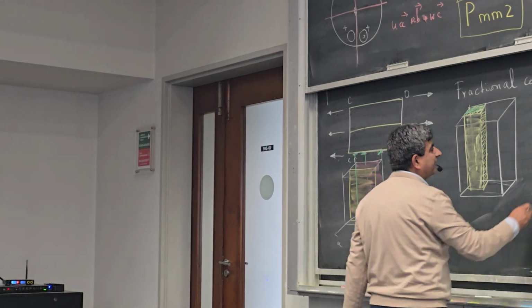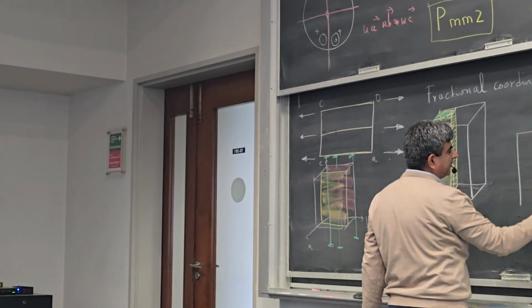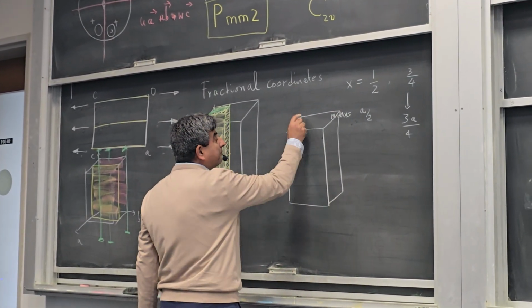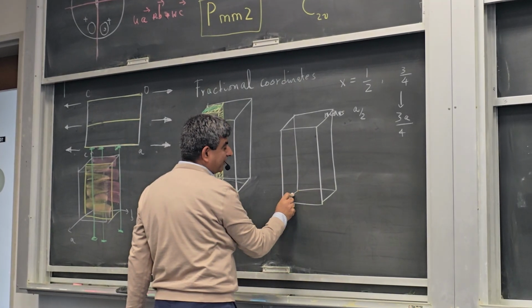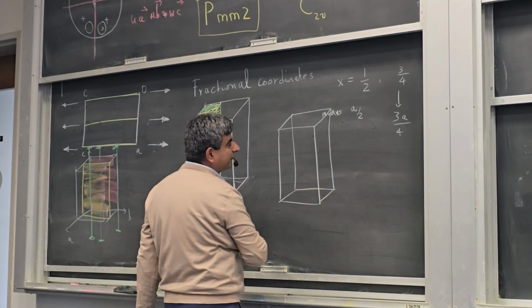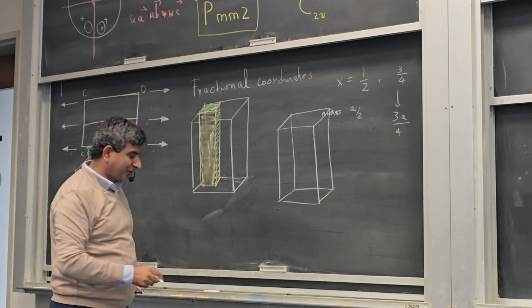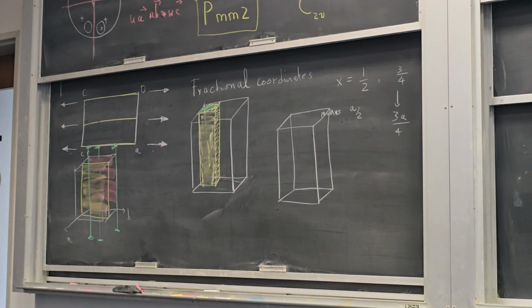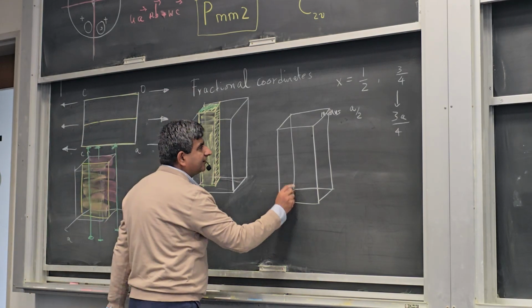Now I'm going to identify the symmetry operations. This is my orthorhombic cell, unit cell, with the particular motif, right? Don't forget that. You can draw different kinds of space using the orthorhombic. So with this particular motif, in the PMM2 group, one symmetry operation is just one, do nothing. The second symmetry operation is a two-fold axis of rotation on 0, 0, Z, which is this line.